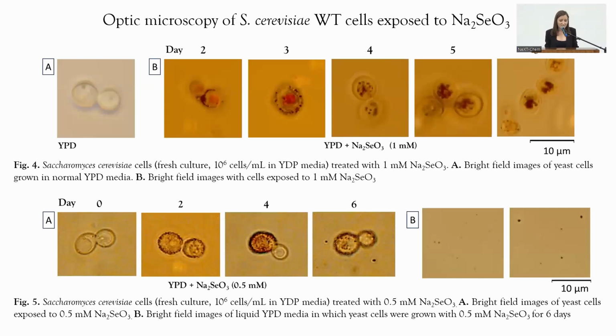We have assessed the influence of sodium selenite on yeast cell growth over a period of 6 days through optic microscopy. And the images we have obtained offered us some intriguing results, showing that after the synthesis of selenium nanoparticles, after the selenium is reduced, the nanoparticles have a tendency to bind to the plasma membrane, and they are slowly absorbed intracellularly. It is probably a phagocytosis process that is happening here. Both sets of images prove this, but they also prove that selenium nanoparticles accumulate inside yeast cells.